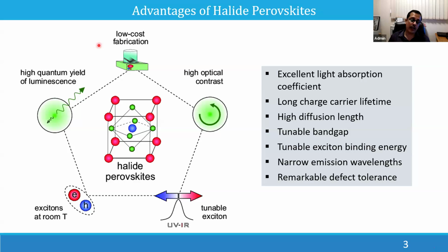Suppose for a photodetector, you may require a narrow band gap, but in some cases you need broadband detection. In that case, you can tune the band gap, as well as the emission wavelength, from narrow to broad wavelength. And also it shows remarkable defect tolerance. For example, there are many quantum dots or nanocrystals based on chalcogenide materials, and these are not defect tolerant. If there are some impurities present in the material, its properties will deteriorate. In this case, that decrease in the property or functionality is not happening because the defect tolerance of these materials is very high.